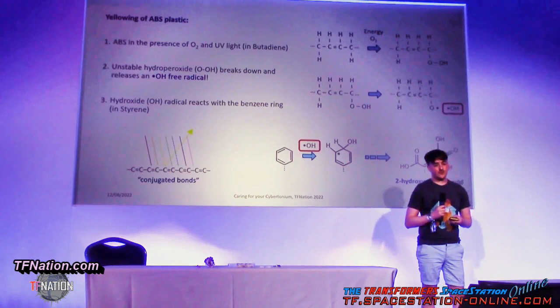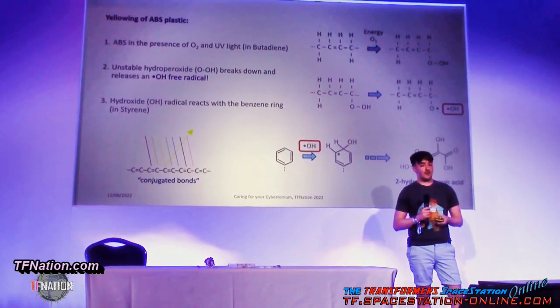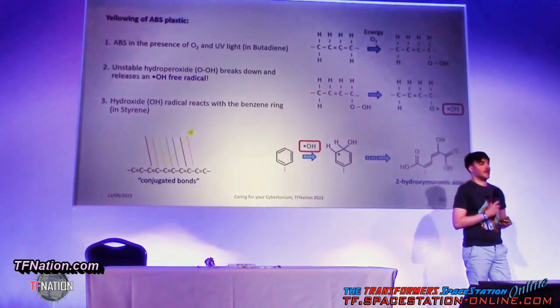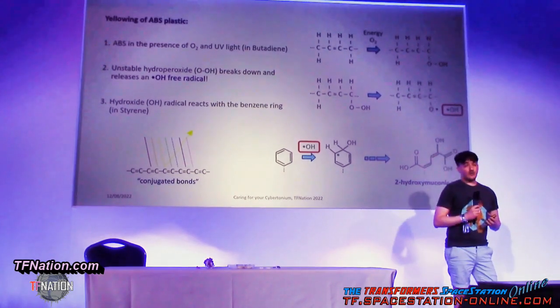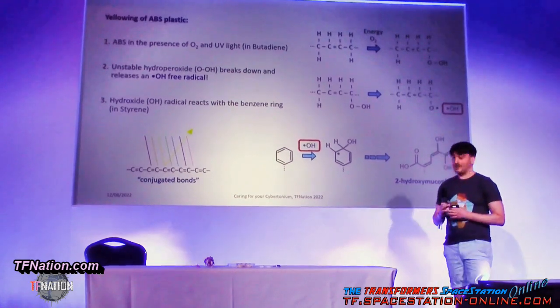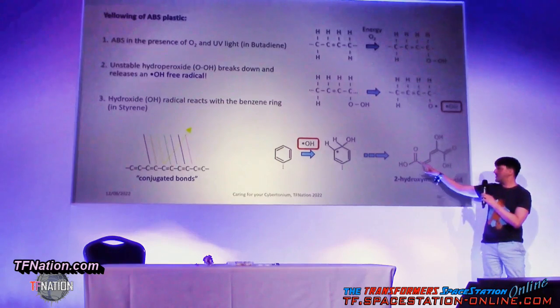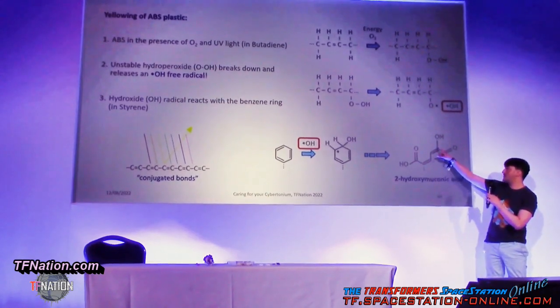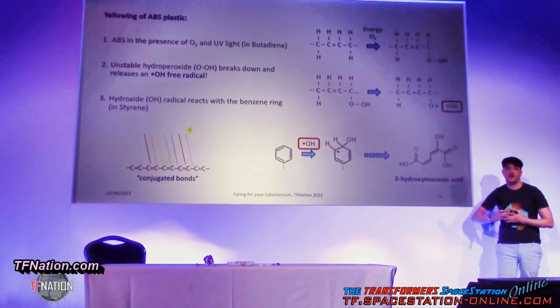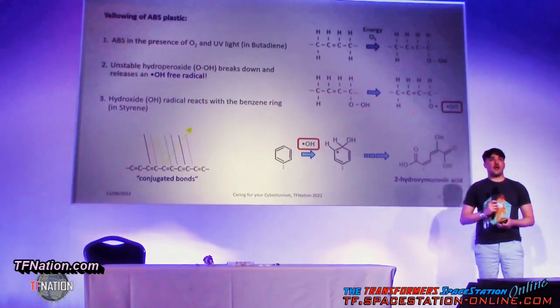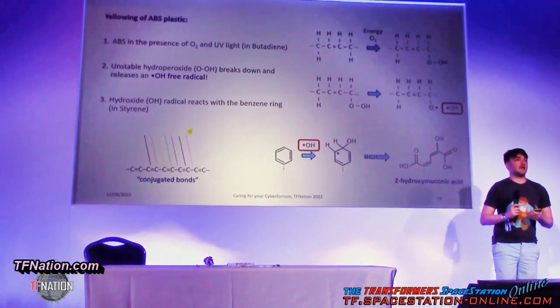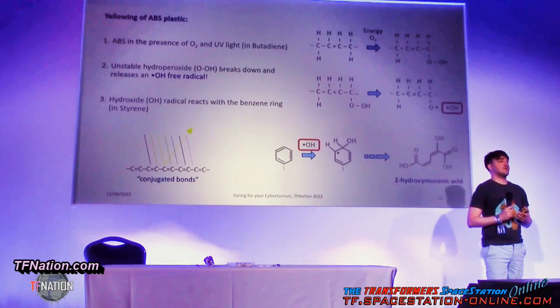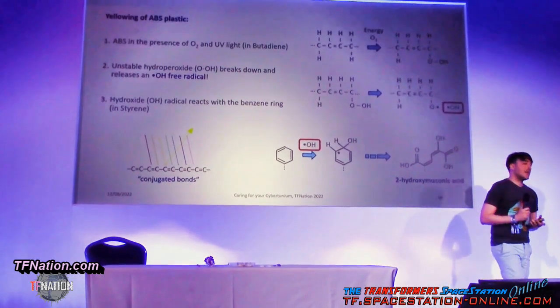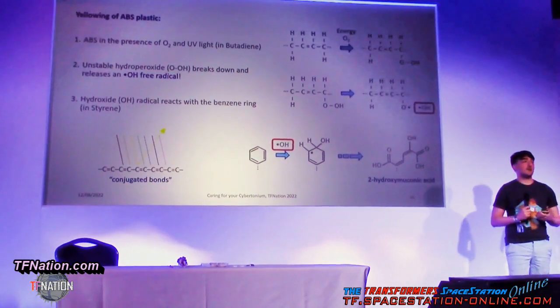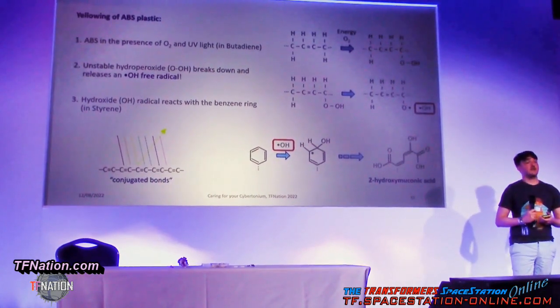What it does is, through a series of about 4 steps, it starts to react and it breaks down that strong benzene molecule, that functional group, and in the end results in something called 2-hydroxy muconic acid, or muconic acid for short. Now the important thing about muconic acid is its shape, so you can see it has a single bond, a double bond, a single bond, a double bond, a single bond, and a double bond. And that is something called a conjugated bond. And because of the vibrating frequencies between the atoms across those bonds, conjugated bonds will absorb everything except for yellow light. So what happens is, by the time you have muconic acid in your plastic, it has become yellow because it is only reflecting or transmitting yellow light.